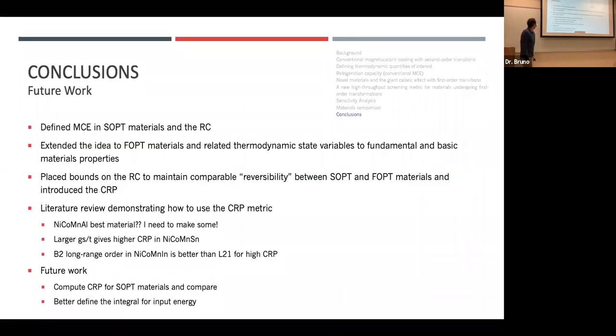So, in conclusion, I defined the magnetocaloric effect of ferromagnetic materials, some thermodynamic properties, and the refrigeration capacity. I extended the idea to first-order phase transformation materials and placed some bounds on my refrigeration capacity and my coefficient of refrigeration performance. Then we did a literature review and collected all this data to compare the different performances of nickel manganese-based metamagnetic SMAs and found that nickel, cobalt, manganese, aluminum, for some reason, gives us a very good CRP. So I need to make some. I have some high purity raw elements, and I just need to arc melt them together and do some study with it. I've used this in the past and found larger grain size to thickness ratio in these materials is better. B2 long range order is better in nickel, cobalt, manganese, indium.